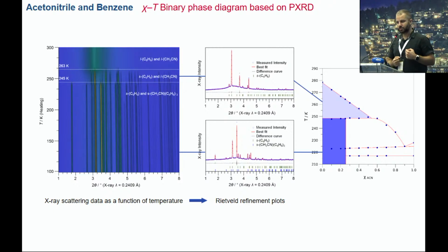However, down there, we see that we have an additional phase, and that additional phase was unknown. That was another big surprise for us, to see something unknown for benzene and acetonitrile. Everyone is using them, you know. I was very proud of this. But we didn't know the structure. Solving crystal structures from powder is extremely challenging, as you might know. Solving crystal structures from powder, from a mixture with a preferred orientation, collected at low temperature is a little bit more complicated.